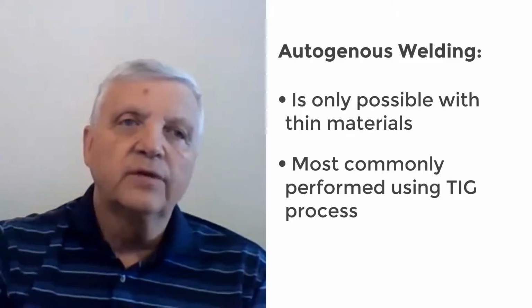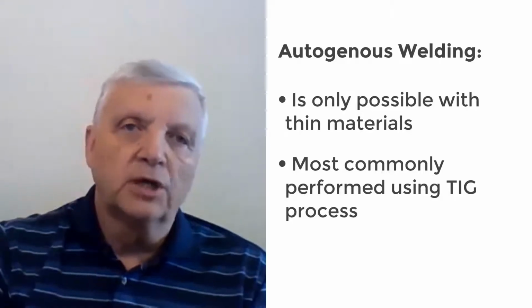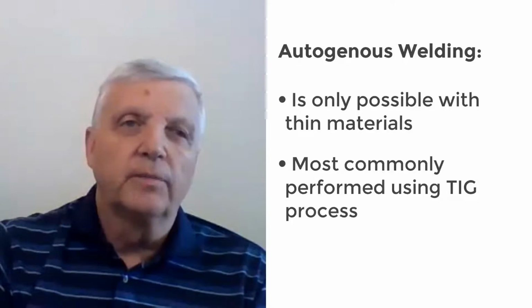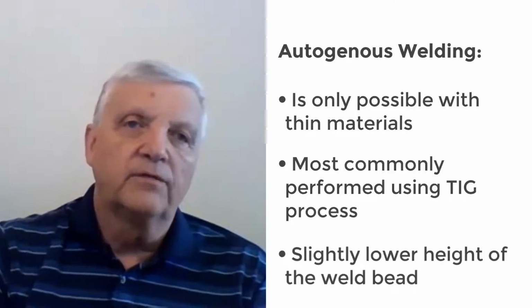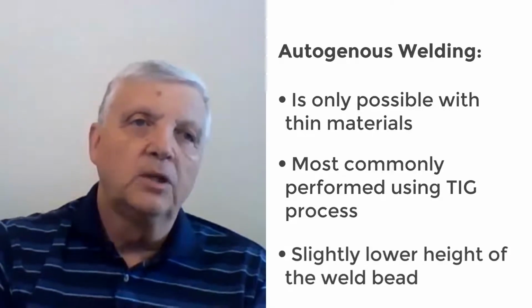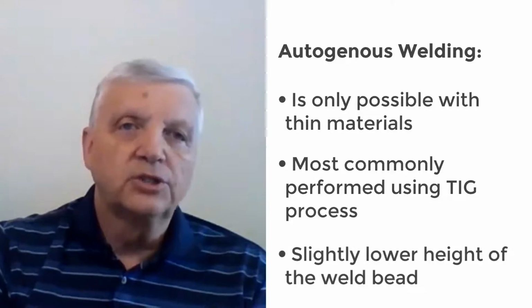There is no significant visual difference between an autogenous weld and a weld using filler metal, other than the height of the weld bead of an autogenous weld will typically be lower because of the absence of the additional volume introduced by the filler metal.